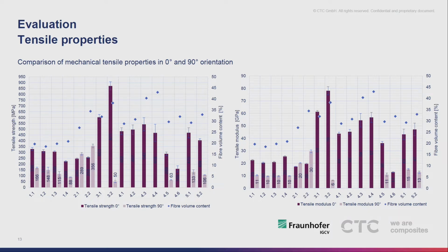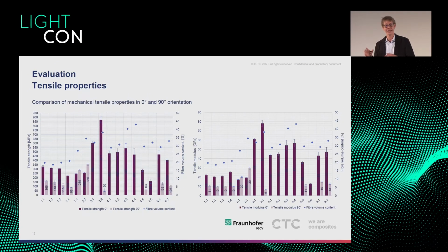The first, let's say, half of this diagram shows you carded textiles. If we divide it by thirds, like 1.1 to 2.2, the first 5 technologies are carded technologies. Those do have a slight alignment, as we've seen in the polar diagram, but they don't really have the good alignment that we've been looking for. Still, we are looking at performance values way over what we've seen in a nonwoven. So a typical nonwoven would have a tensile strength of 120 megapascal at the most. With even the bad textiles of the oriented carded textiles, we achieved something in the range of 300 megapascal. So a 2 to 3-fold increase just by slightly combing those textiles.